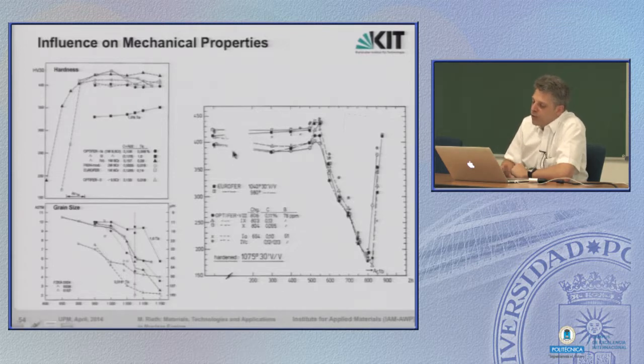Then if you have produced this hard, untempered martensite, you can temper it, and this is shown here with increasing temperatures from 200 to 900°C. First, nothing happens until around 600°C, and then the softening starts. And this is the temperature range where the carbon diffuses out of this tetragonally distorted BCC lattice, and this makes the martensite more and more soft and also more and more ductile. And the optimum or the end is reached near 800°C. It's around this value. If you exceed this temperature, then you produce fresh martensite, and then the curve goes up, and here it's continued.